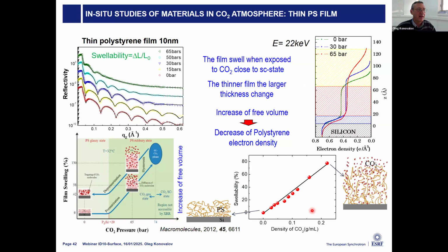And this is an example of application of a CO2 sample cell to see how it affects polymer films, that they absorb, they change thickness, and even after we release the CO2 completely, there is a change of the structure, and also there is some rest of CO2 which is trapped by the system even at zero